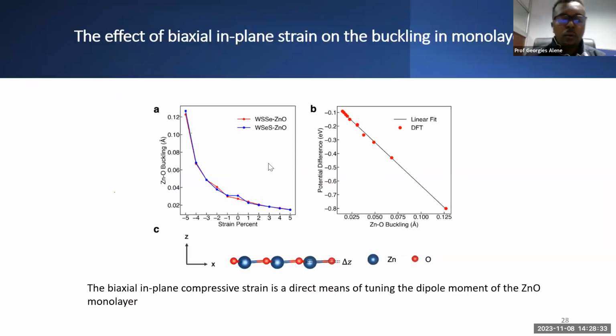For the zinc oxide, we have also studied the effect of biaxial in-plane compressive strain on the dipole moment of the zinc oxide. Here, it says buckling. Buckling means the z-axis separation between the oxygen and the zinc. So you can draw a plane, and this separation is called the buckling. And this buckling is actually affected by strain. When we apply compressive strain, for example, negative 5%, you can get like 0.12 angstrom buckling.